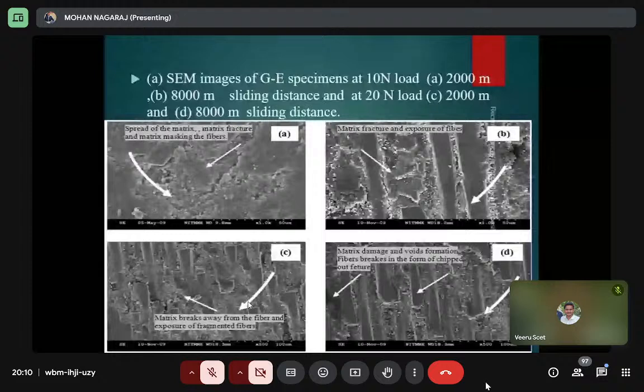Here we can observe this is more evidence we are observing in the scanning electron microscope. So the summary of this natural filler material filled in the glass epoxy composite strongly depends on the experimental test parameters, sliding distance and applied load. Wear losses increase with increases in sliding distance and applied load.